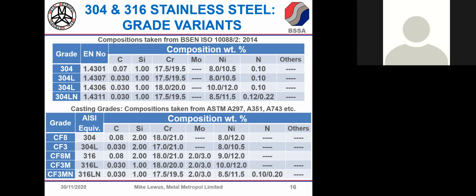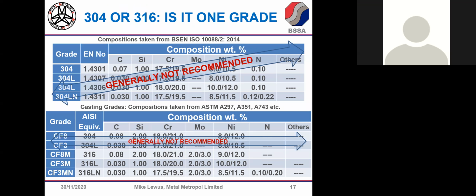Similarly with 304, there's more than one grade with that tag. And we also have cast grades. I'll quickly say that if someone asks me about what grade a component should be made from in a marine environment, and I'm talking about a marine atmosphere, unless somebody's not the least bit bothered about aesthetics and it's not a safety critical component, I wouldn't generally recommend 304. That's not to say you won't find 304 used out there, but you'll soon know if you've got 304, because it won't take long for the surface to degrade.